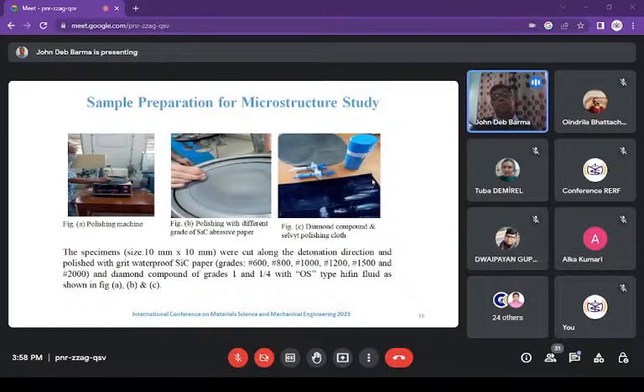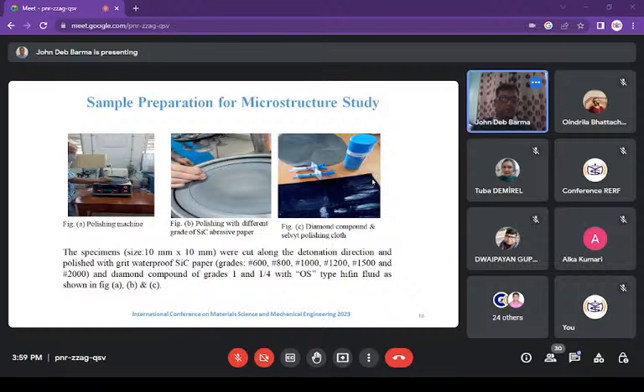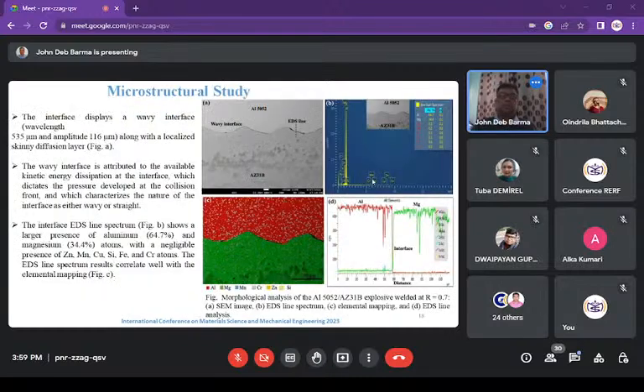Now, certainly after welding, we have gone for sample preparation in order to carry out the microstructural study. So specimens were cut along the detonation direction and polished with grit waterproof silicon carbide papers, 600, 800, 1000, 1200, 1500, 2000, and certainly diamond compound of grades 1 and 1/4 with OS type hifin fluid has been used for surface preparation for doing the microstructural study.